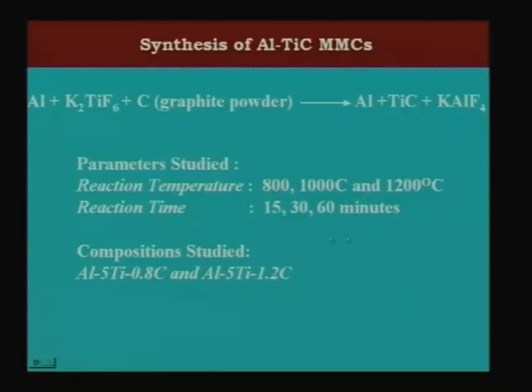And again here the composition has to be controlled, the temperature and the reaction time, both of them have to be controlled, so that you end up only with this. Here I show you an example of two such compositions, one where it is 5 titanium, 1.2 carbon. If you carefully observe, the ratio is again very close to 4:1. In fact, if it is 4:1, it has to be 4.8. This is the initial chosen composition. After the composite is made, the actual titanium content is about 4.85, which is very close to what is expected. And here you see the ratio is more than 4:1. So, because of which you end up probably with some Al3Ti. So, that is what we want to see here.